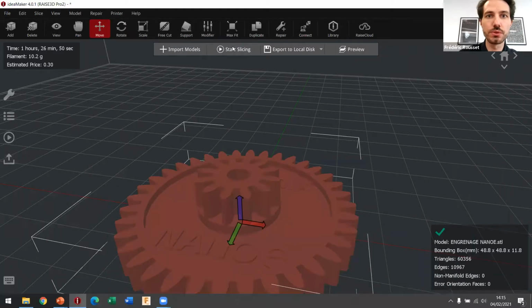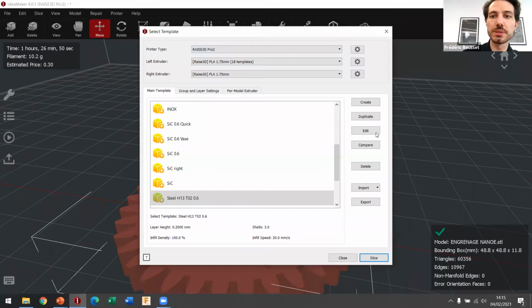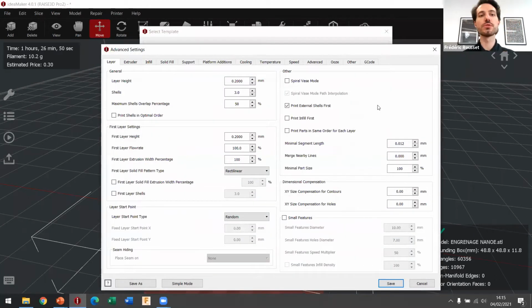So right now, I showed you the preview. I'm going to show you a bit more of the different parameters that we have. The parameters that I have put in this template are for the H13 with a nozzle of 0.6. It can vary a lot depending on the size of the nozzle you're using or the material, of course, but this is for the example. I think I'm going to show about 10 different parameters. There are a lot of them, but I'm just going to show the most important ones. First of all, the layer height. The layer height is very important. It depends on the nozzle that you are using, of course. I'm using 0.2 for now. You can go from 0.1 to 0.4, depending on what you're using.